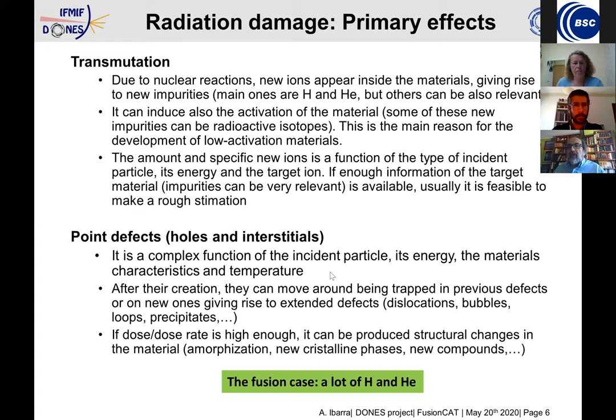Of course, later on, these primary defects can move around, and due to this movement, they can aggregate, they can be frozen in different positions, and this gives rise to a huge number of different types of macroscopic defects in the material, like dislocations, bubbles, precipitates, and so on. In the case of fusion, the main thing that we have is these vacancies and interstitials, and due to the energy of the neutrons we are talking about, a significant amount of hydrogen and helium is produced in the material, and we need to take into account these effects in the materials, the presence of hydrogen and helium, and at the same time the generation of point defects.